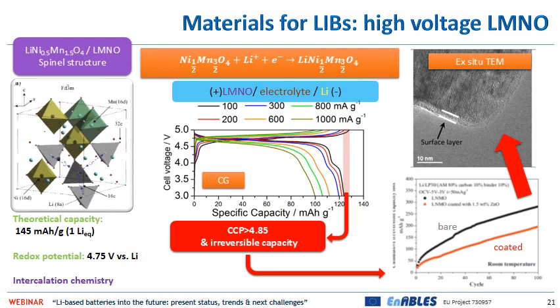However, this very high redox potential is a drawback, because at such high redox potential, the electrolyte oxidizes in part cycle by cycle, and the surface layer, that is a passivation layer that is forming over the surface of the material, is not able to fully prevent the degradation cycle by cycle. That's why the research is looking for coatings over the particles of this lithium nickel manganese oxide, in order to mitigate or limit the degradation of the electrolyte and the accumulation of cumulative irreversible capacity.